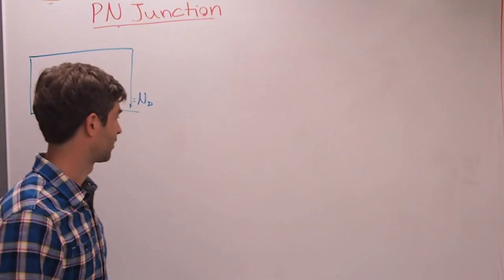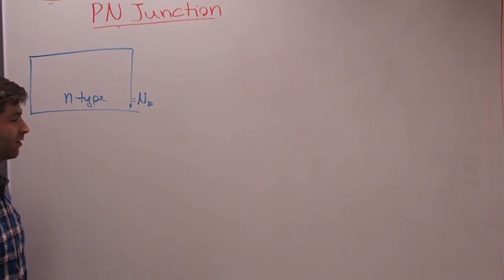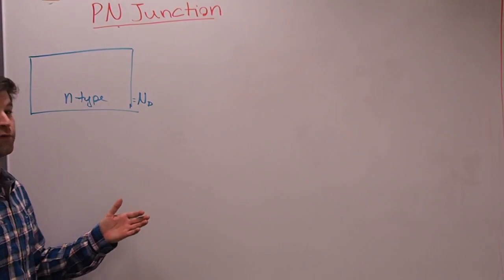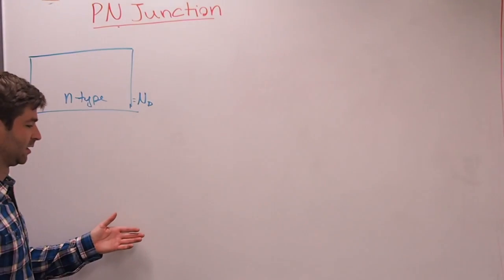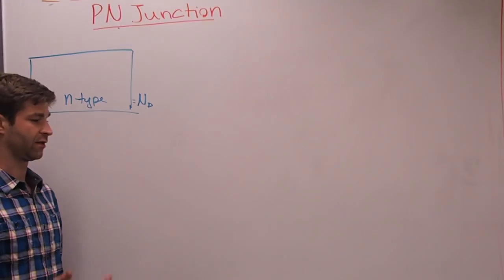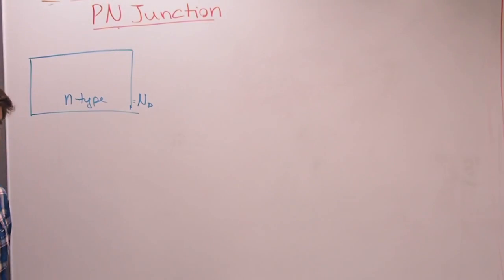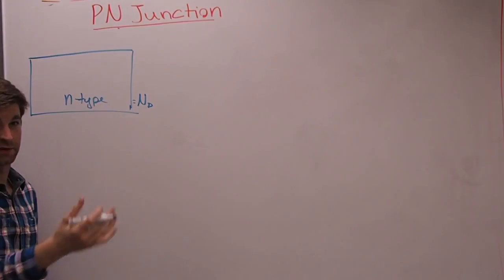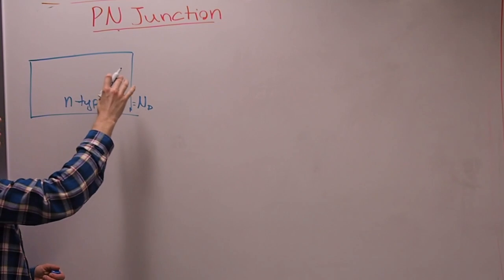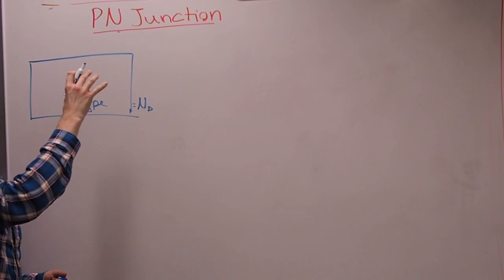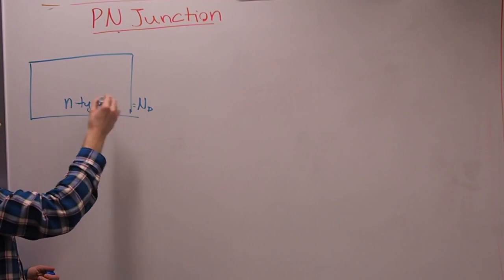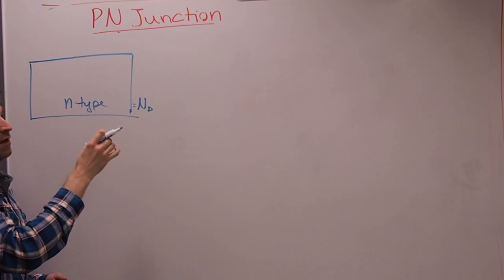So we're going to start with this N-type silicon, right? N-type meaning donor doped, meaning it's doped uniformly with atoms that have an extra electron. And then through a process called diffusion. Nowadays they use something called ion implantation, but in the olden days, well, not that old, they still do it in some fabs, they would coat this top layer with a photoresist, and they would create an opening right here, and then etch away the photoresist, and then they would grow an oxide.